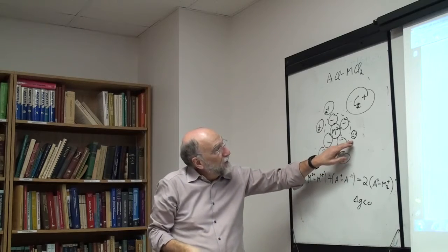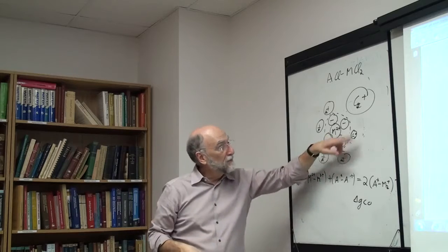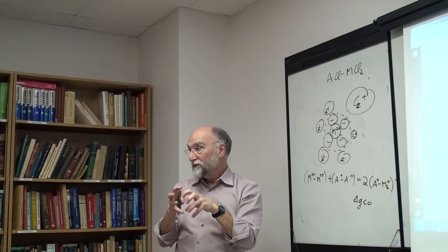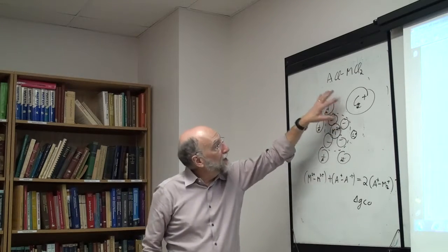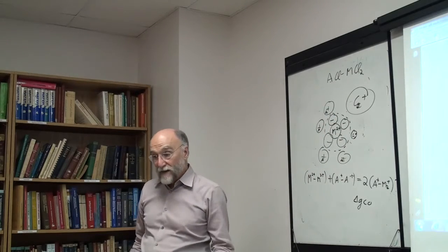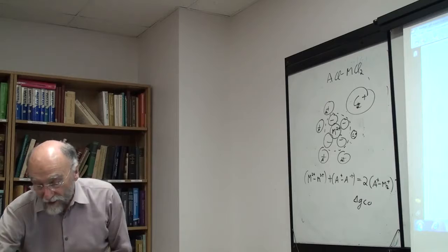If you have small lithium ions, they compete with the magnesium ions for the chlorine and try to form their own semi-complexes. But if you have great big ions out here, the magnesium tends to surround itself with chlorine and the big cesiums, and that keeps the magnesiums apart from each other, and it tends to be more towards the ordering.